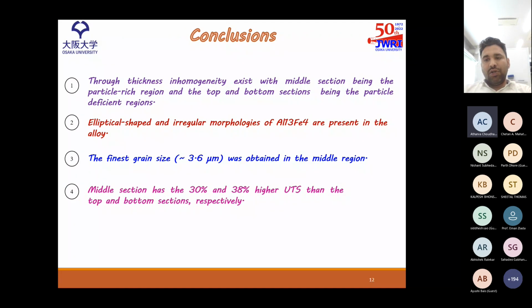Coming to the conclusion of this part of the presentation, we have obtained the through thickness inhomogeneity, and the middle section is the best section, and it has the highest strength. Two types of morphologies are found, that is elliptical shaped and irregular morphology, and the finest grain size was obtained in the middle region.